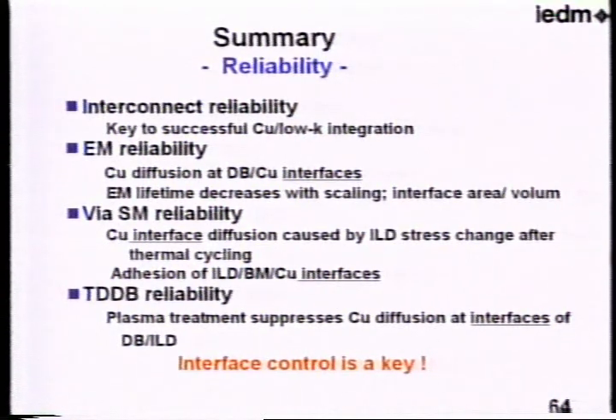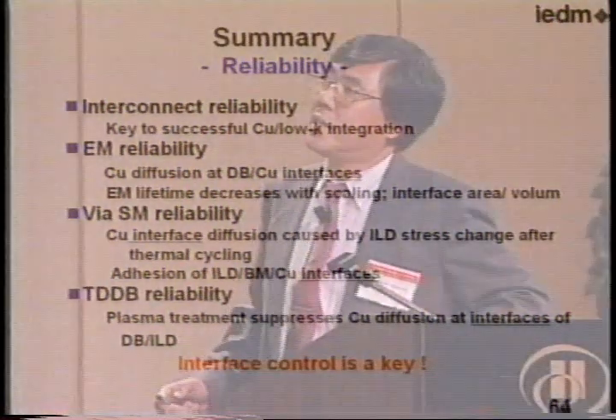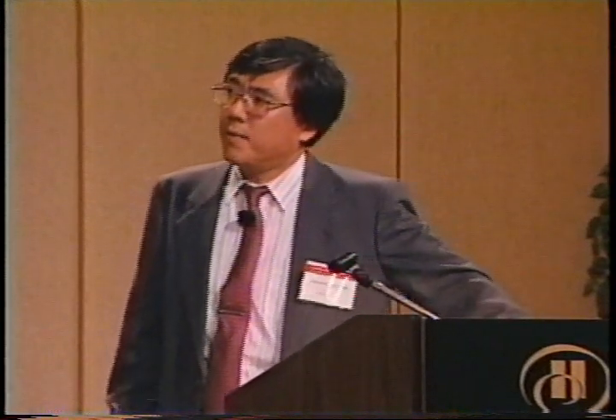I'll summarize the reliability section. Interconnect reliability is key to successful copper low-K integration. For EM reliability, the lifetime decreases with scaling. As for the SM reliability, copper interface diffusion caused by ILD stress change after thermal cycling is an origin for this reliability issue. Therefore, the adhesion of ILD, barrier metal and copper interface is very important. As for the TDDB reliability, plasma treatment is very effective.